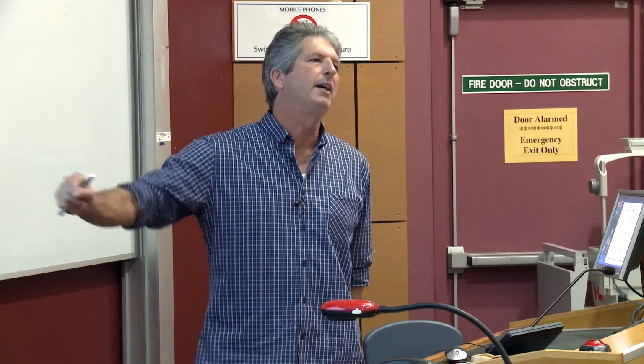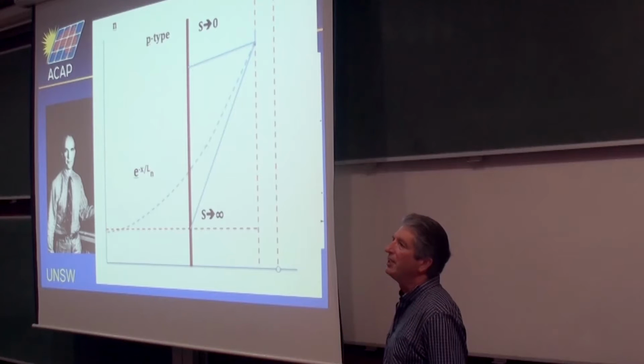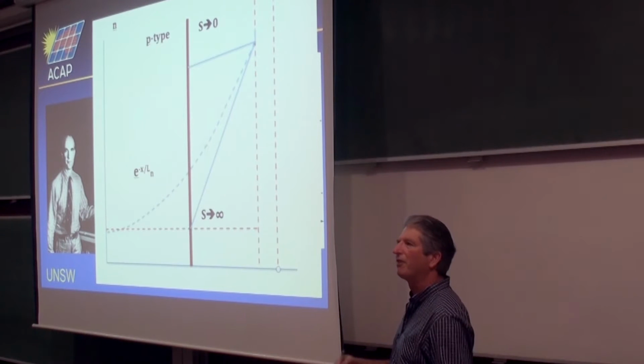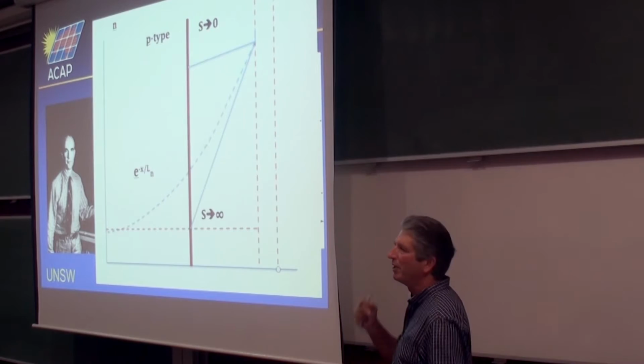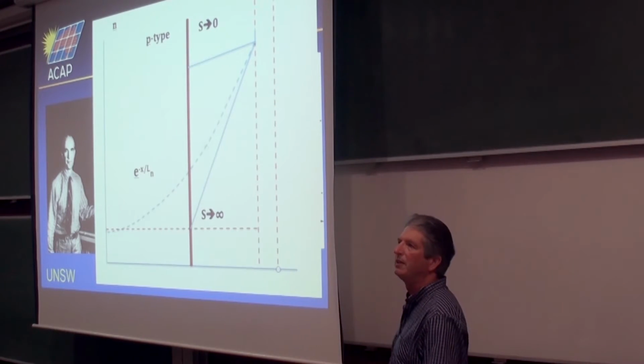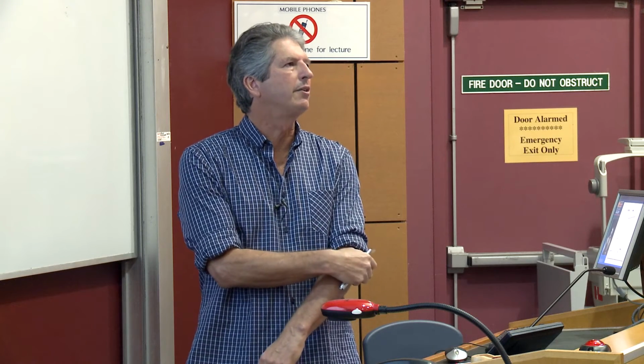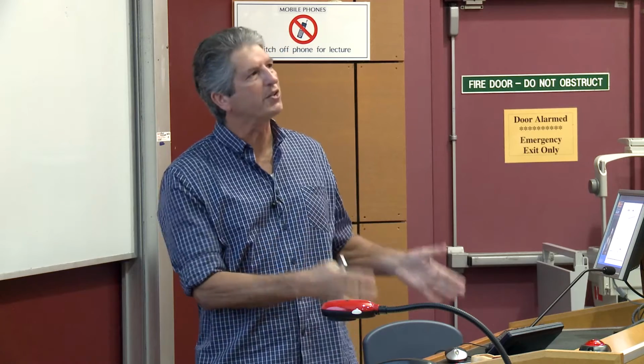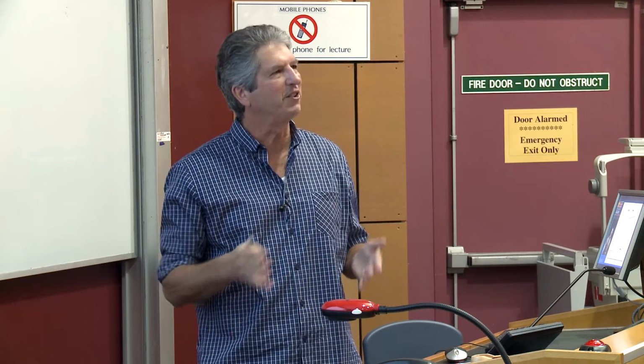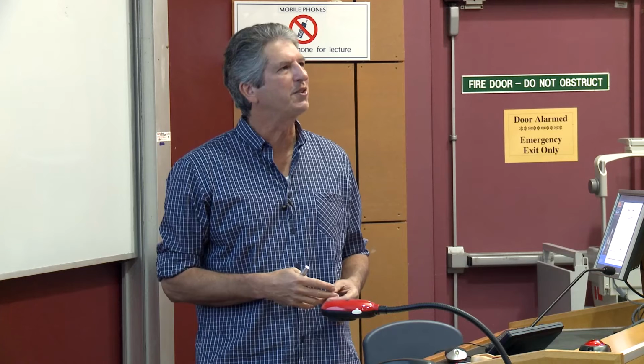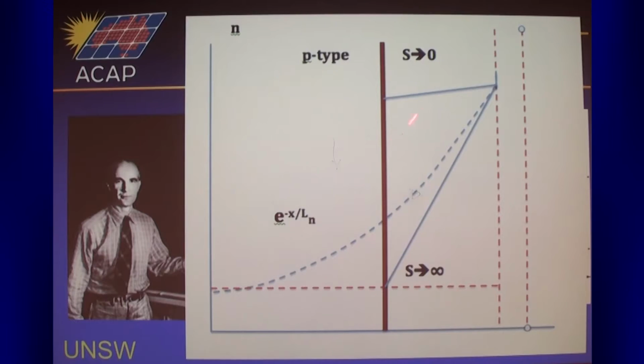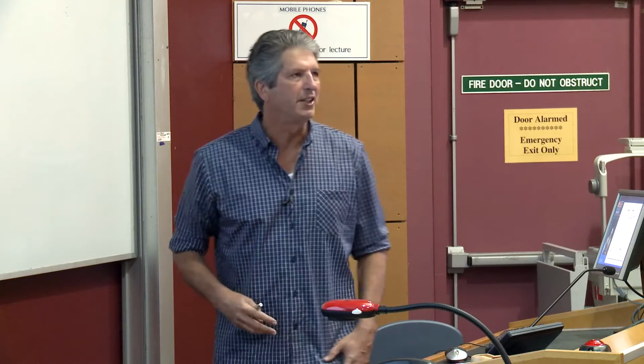It turns out a 10 times decrease in current flow, which I'm talking about, corresponds to a 60 millivolts increase in open circuit voltage. So if you've got a solar cell with 600 millivolts open circuit voltage, a 60 millivolt improvement is quite substantial. So this is the type of thing you can get by controlling the surface recombination velocity, like a 10% supercharging of the cell performance.